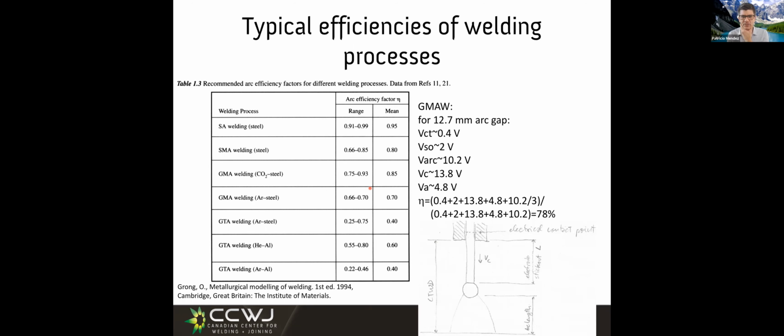Lower, good. I have a suggestion for lower. And of course, because if I increase my arc length, that means a higher amount of energy is going to be radiated out and lost, right? These tables here don't say that, but we know it, right? Look, question. Well, not a question because we have the answer.